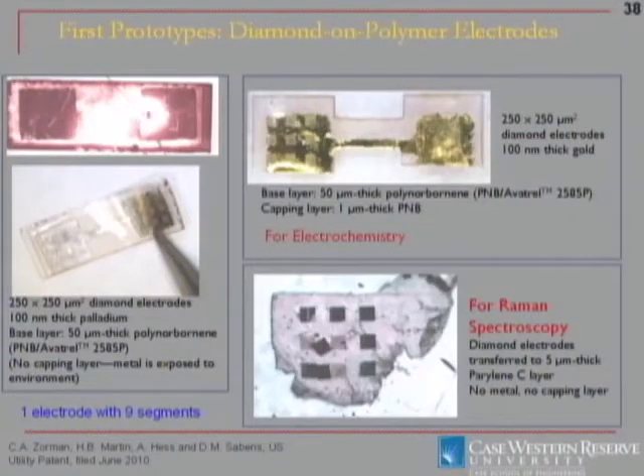So the other strategy involves putting diamond with a polymer. And again, I said we can't grow diamond directly on it. So what we've done is develop a transfer technique for doing this. And this, again, is with Chris Zorman and with award-winning Allison Hess and David Sabins on my side, who's a winner to me too, right? And so we have here some first prototypes. This is a diamond, 9 electrodes, or it's 9 pads as 1 electrode with a palladium contact.